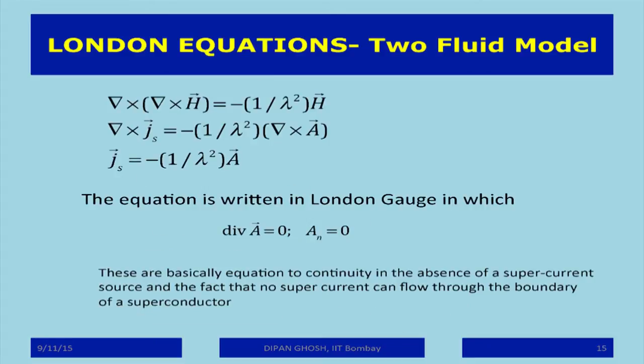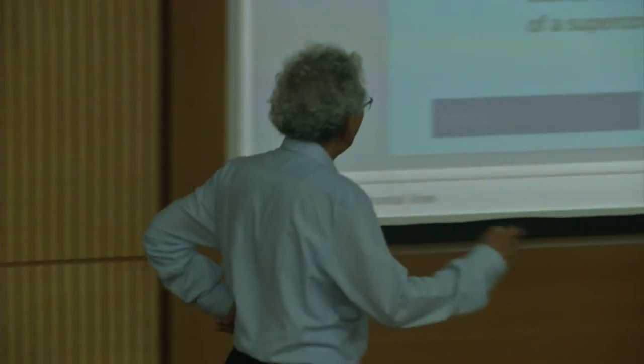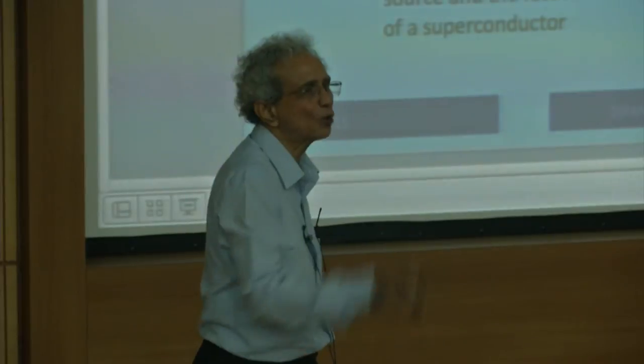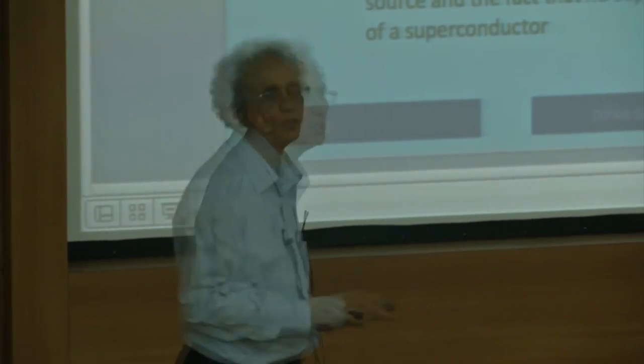I had del cross H equal to minus 1 over lambda square H, and so therefore this is what happens. Now if you wanted to convert this into an equation in J, then reproduce for del cross H your J, and this becomes that your J and the vector potential are linear with each other. This is called London gauge. The divergence of A and the normal component of A become equal to 0. You need the normal component of A equal to 0 because you don't want any current to flow across the superconducting boundary to the normal state.